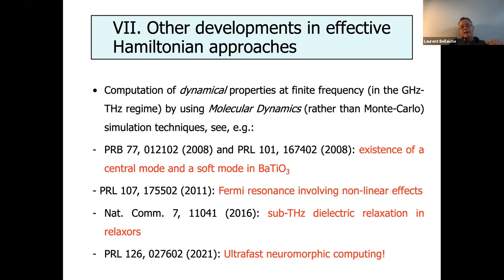You can also do very nice physics, like nonlinear effects, like Fermi resonance. This was done by Dawei Wang, for example, in this paper. And in 2016, also with Dawei as first author, we looked for the first time at relaxors and dielectric relaxation. It is a very strange system. Basically, the dielectric response depends tremendously on the frequency of your applied electric field, unlike in ferroelectrics, and the effective Hamiltonian was able to reproduce these effects, which are also important in the terahertz or sub-terahertz regime.